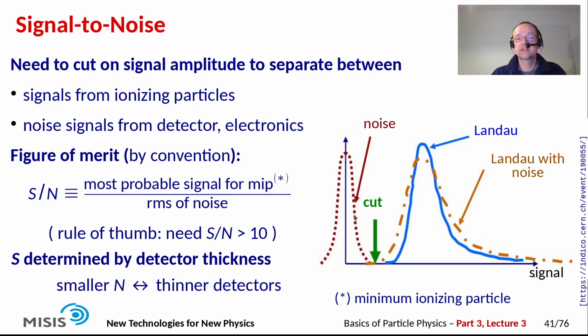The figure of merit that is used to measure the signal-to-noise performance is the ratio between the most probable signal for a MIP, so essentially the peak of the Landau distribution here, divided by the RMS of the noise distribution. These are two quantities that can easily be measured in a detector. As a rule of thumb, according to this definition, you need a signal-to-noise of at least 10 or better in order to have a functioning and efficient detector. Now note that the position of the Landau distribution, so S, is determined by the detector's thickness. So if we can make the noise N smaller, we can also afford to make the signal S smaller, and that means we can afford to make our detectors thinner, which is of course beneficial to reduce multiple scattering and energy loss of particles in our detector.